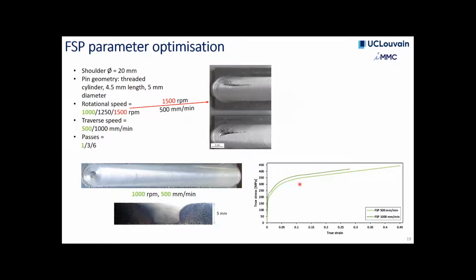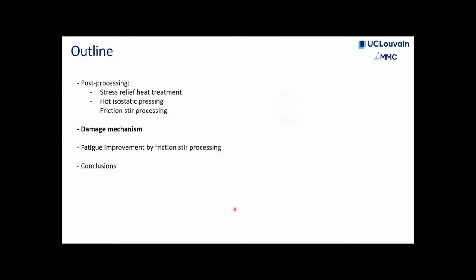And we used here the different parameters. I'm not going to show you a lot of details of different parameters, but just to show you that we had to optimize these. And so we finally selected the 1000 RPM and 500 millimeters per minute conditions. And if not mentioned differently, these are the ones that were considered, but we also tried another one. I'll show you minor results on this.